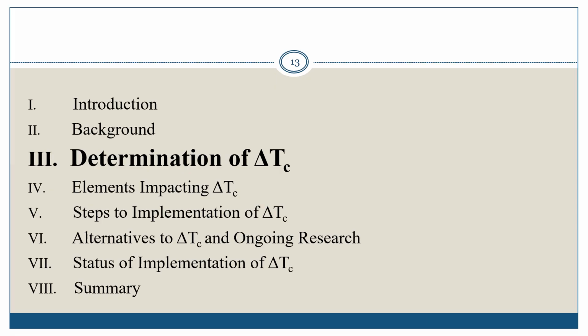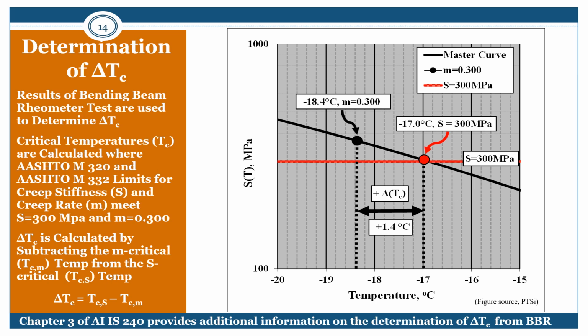How is delta TC determined? The delta TC parameter is an indicator of how effectively asphalt binder responds to aging and how incorporation of additives may impact the response of asphalt binder to aging. Delta TC is represented as the difference in critical low temperature values of asphalt binder according to the Superpave performance grading methodology. Results from the BBR test, AASHTO T 313, are used to calculate delta TC.